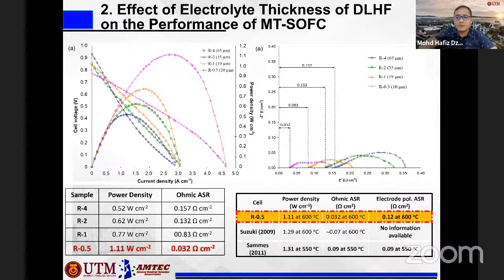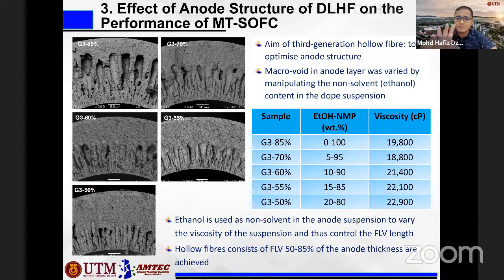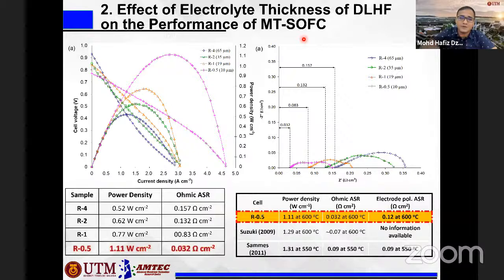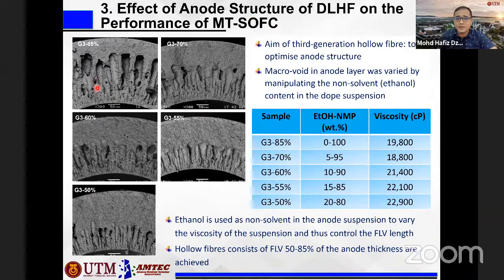Based on the comparison with literature, our performance of 1.11 is a little bit reduced compared to the literature. So how do we improve further? We can alter the anode structure by mixing ethanol and NMP as a solvent in our dope suspension, because ethanol is considered a poor non-solvent. Increasing the amount of ethanol in the solvent will increase the viscosity of the suspension. When the viscosity increases, phase inversion is less likely to happen, or it happens only on a very small part.